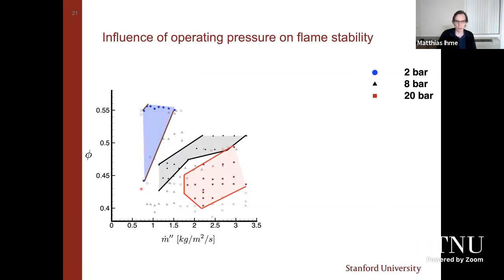Again, same diagram. This is done at different operating conditions. I'm plotting the equivalence ratio as a function of the mass flow rate. What you're observing here is significantly higher mass flow rates. We can push about 3 kilograms per square meter per second through the system. And with increasing pressure up to 20 bars, we can also operate this at much cleaner conditions. So this makes it very interesting for practical applications. We can push this to rather low operating conditions.